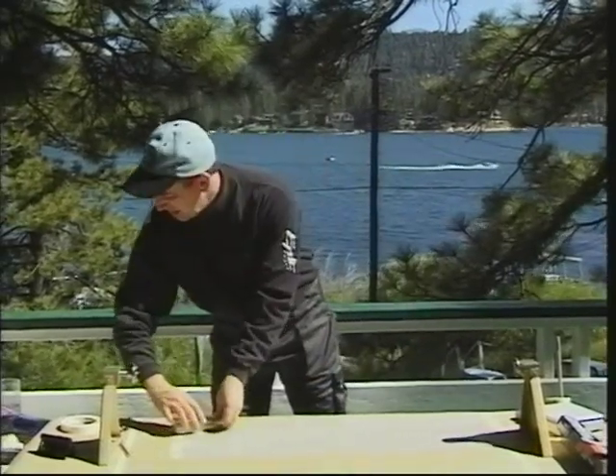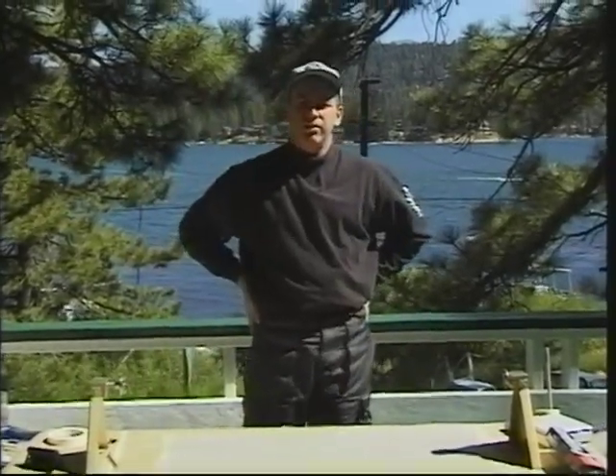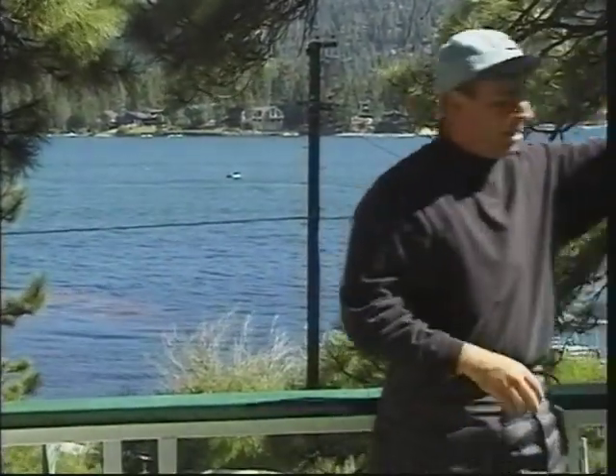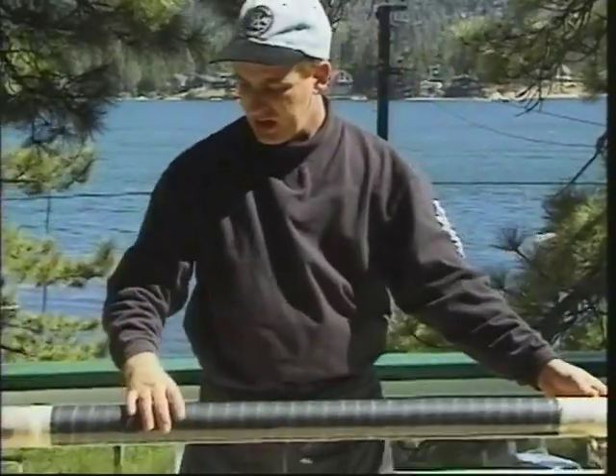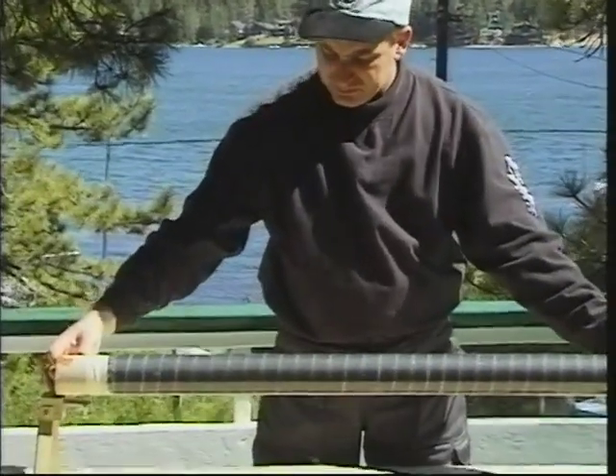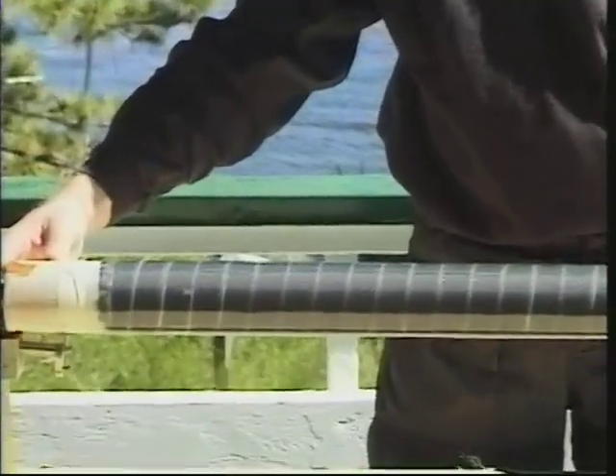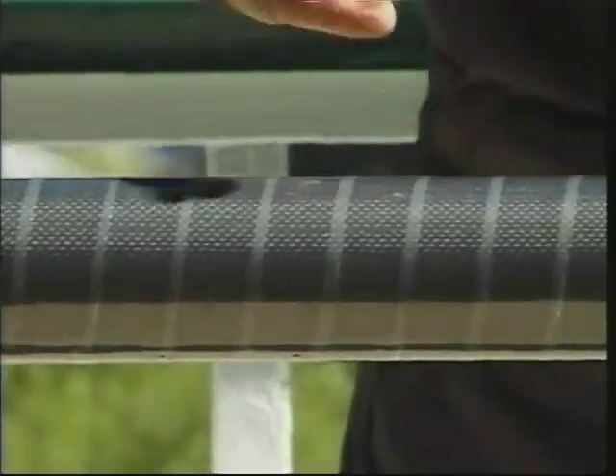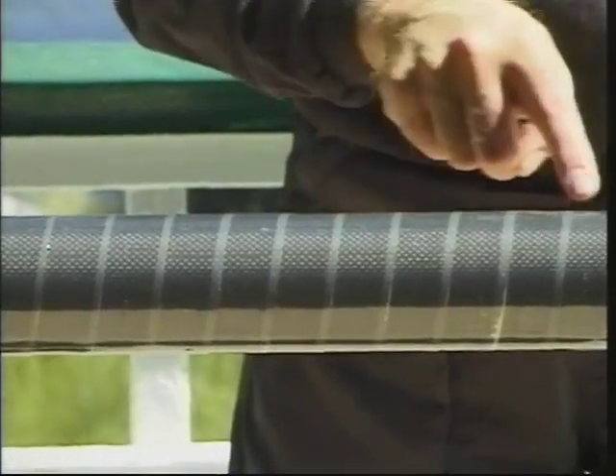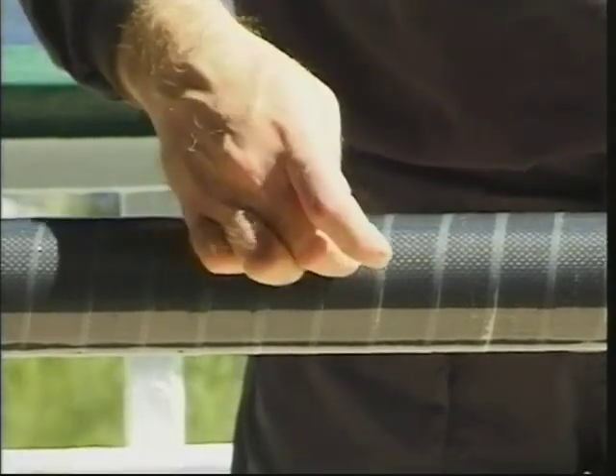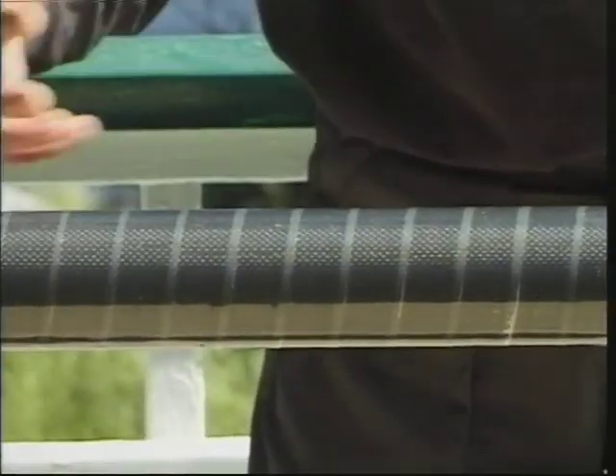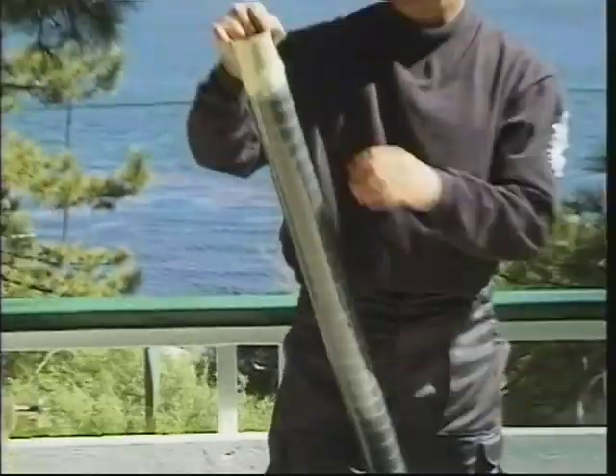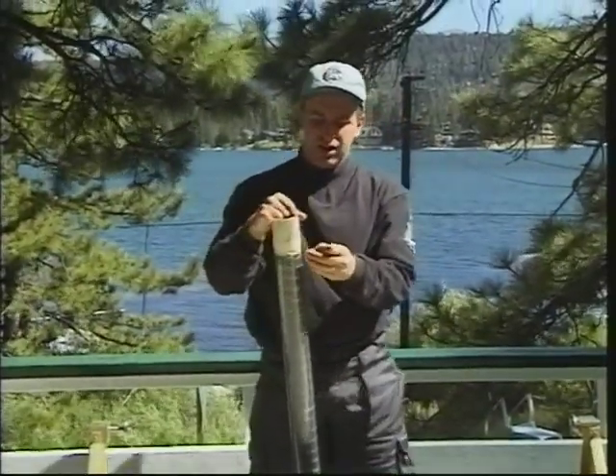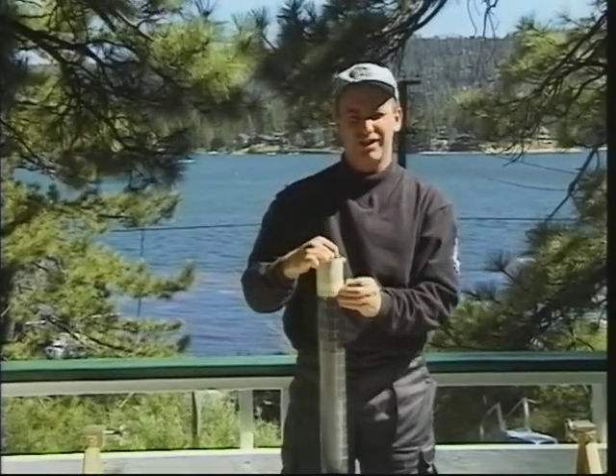Now, let me show you a couple results of what that carbon fiber looks like when it's done. I've got one finished here that still has the heat tape on it. Now, if we can zoom in on that tube, what you'll see is that the heat tape has constricted around that tube. It's bled off any excess resin. There's no air bubbles under here. The excess resin is on the surface of the heat tape and it's all cured up. So let's take that off and see what it looks like. And we'll just show you how to remove it once the heat tape's done.